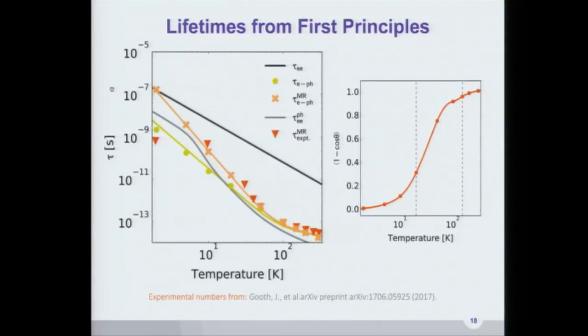And here, we're looking at different contributions of lifetimes. This is going from high temperature to low temperature. This is going from low lifetimes to high lifetimes. And these are the different contributions. And these orange triangles or inverted triangles are what people had experimentally measured, right? So the assumption with hydrodynamics is that there's something that is scattering but is not allowing the momentum to be randomized. That's how there's some kind of collective flow, rather than there being kind of things that resemble typical transport.